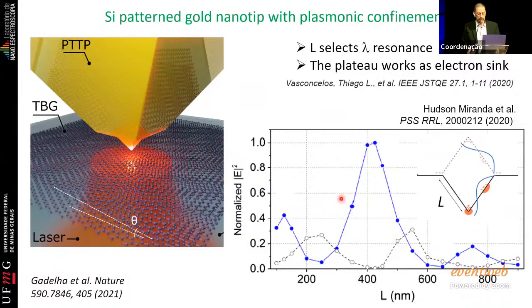Okay, so this is a calculation made for a He-Ne laser, that is the red, the usual laser that you have in laser pointers, showing that when you change the size of L, you have resonances, and these resonances are related to matching half of the wavelength in this plasmonic wave. And we have a maximum here that happens when you have exactly L equals 400 nanometers.